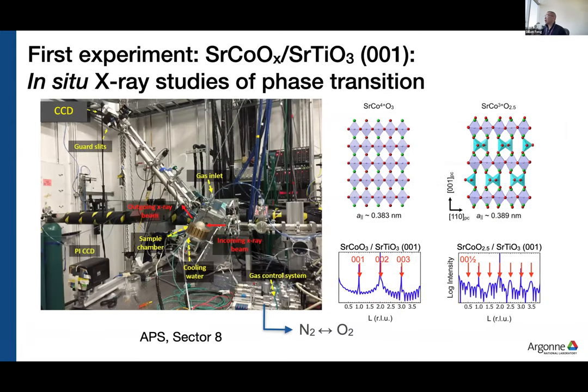I'm really going to discuss work that's several years old, but we started off with strontium cobaltite grown by PLD on strontium titanate 001. So it's all epitaxial. This was grown and then put into this furnace, which I'm showing at the center of this diffractometer. This furnace allows you to switch between nitrogen and oxygen. I'm showing the gas control panel there.